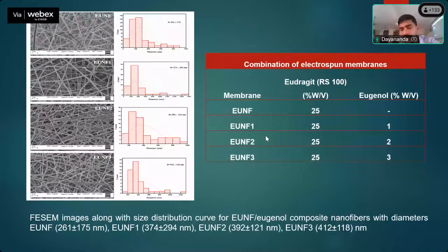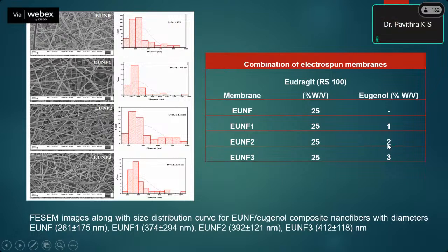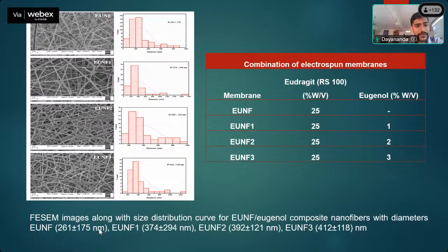In the second case, 1% eugenol was loaded. Next, 2% eugenol was loaded, and 3% eugenol was loaded. That is why the nanofiber diameter was also different for different nanofiber mats. See that branched structure here - there is no bead formation, which tells us the condition was properly optimized for our application.